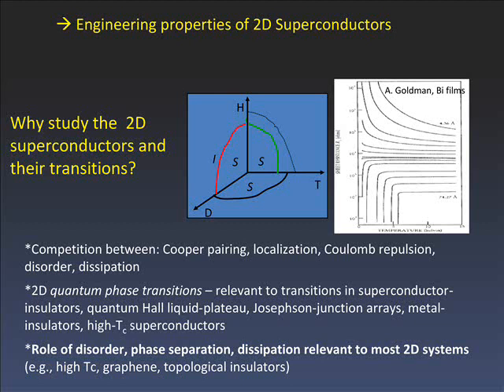These systems are expected to undergo transitions from superconductor to insulator states, or sometimes superconductor to metallic states. These transitions are tuned by disorder, magnetic field, and temperature. Here you can see an example from Alan Goldman's group — a canonical superconductor-insulator transition, a quantum phase transition between a superconducting and insulating state as you approach zero temperature. These zero-temperature quantum phase transitions are common in condensed matter systems, making this a paradigmatic system.